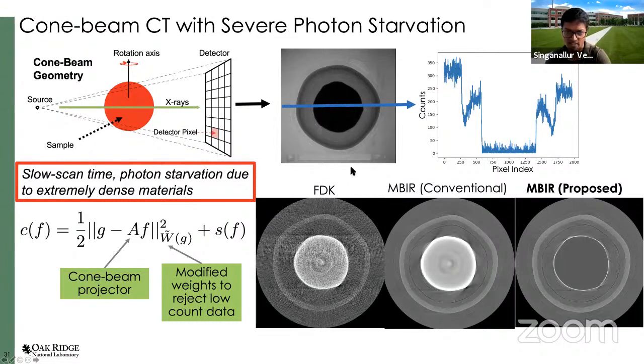If you just plug this kind of data into a standard reconstruction technique like FDK, you're going to get a lot of noise because of photon starvation. If you use the conventional MBIR techniques with the conventional weight models, you can still do a pretty good job already, right? Because it naturally weights down projection measurements that are of low count. But by modifying the weights, you can further reduce the artifacts that can occur, for example, here, if you look. And that can be important because in this application, they're interested in characterizing what is in the cladding. So the summary is we've again been building solutions where by using these model-based approaches, we can do much more.